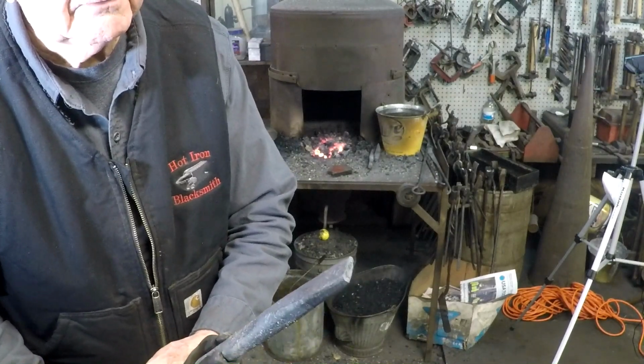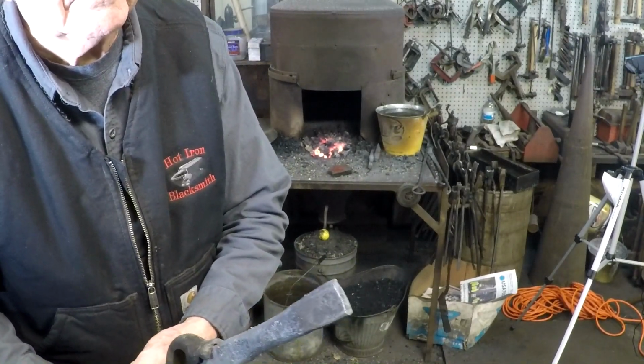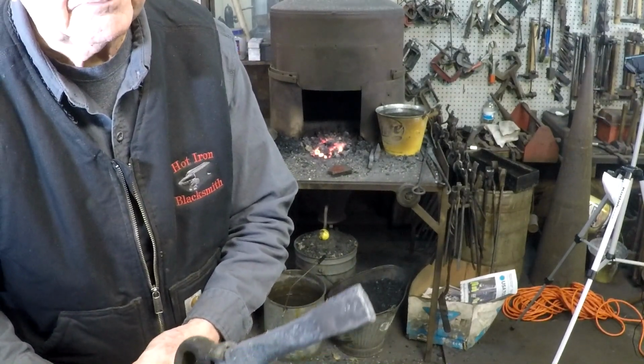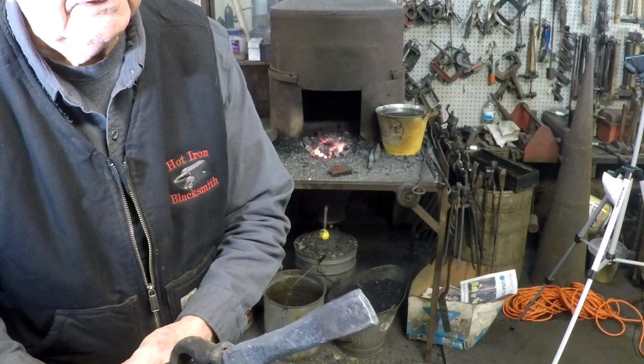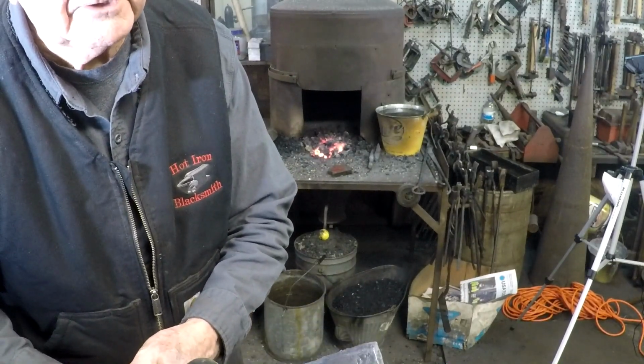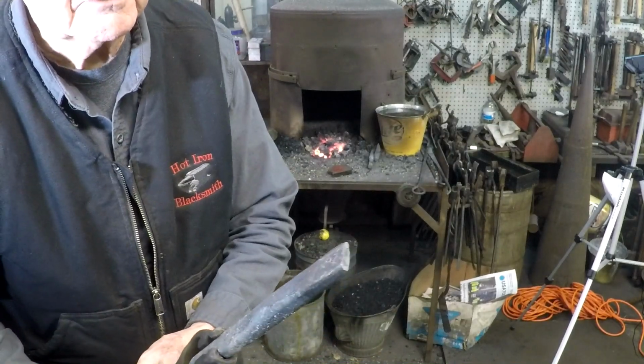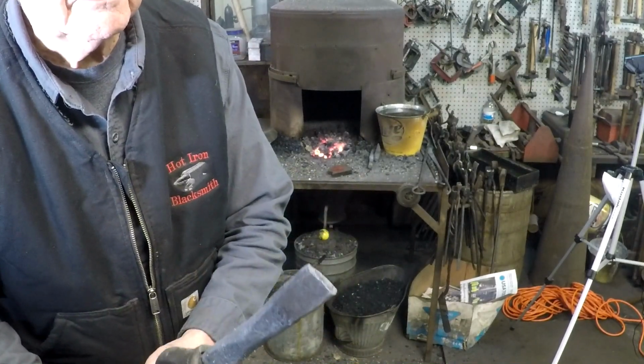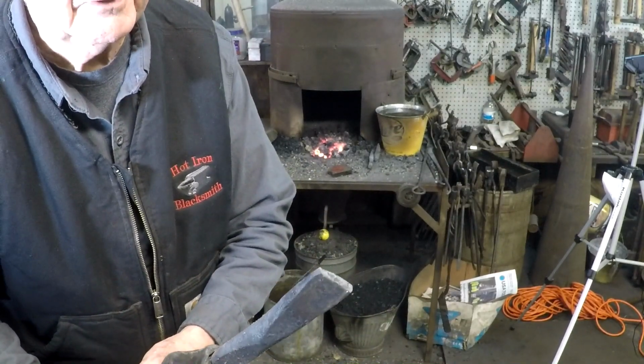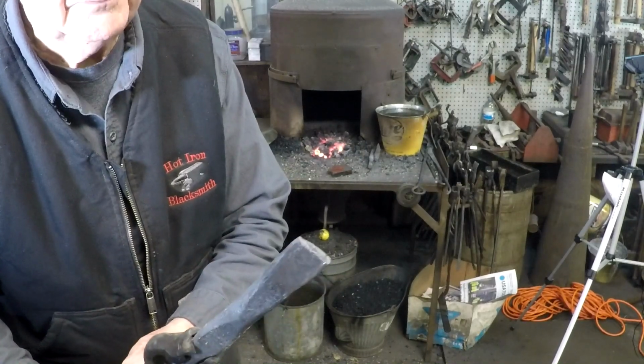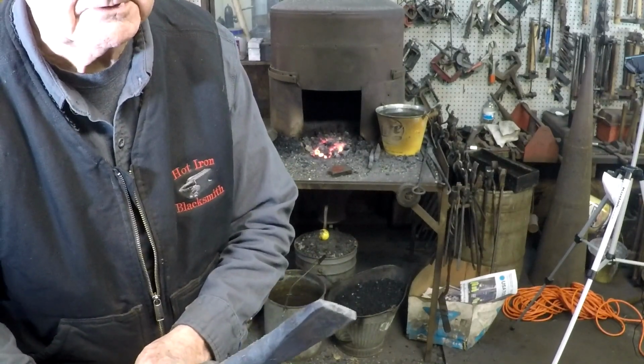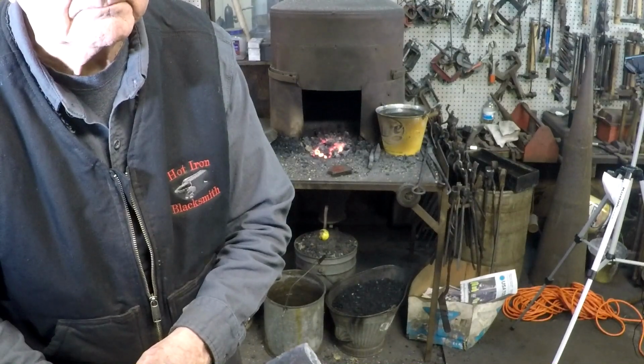So if we don't get the heat transferred all the way down, essentially there's 30% of the steel that could be in a brittle phase, and so this is just a cover-all insurance policy to make sure we get the best result possible with the steel that we're using.